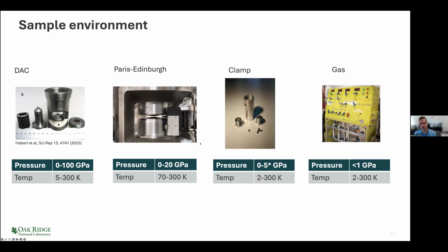We have quite a diverse range of sample environments, which we can plop into the instrument. So on the left here is the current iteration of diamond anvil cell. These were specially developed using funding from the first E3, and then I think probably the second E3. And this was very much led by Reini Bowler, who recently retired, but is still active in the field. And these have been demonstrated to exceed 100 gigapascals, and we've measured neutron data in that regime, which has been quantitatively refined to give meaningful structural information.